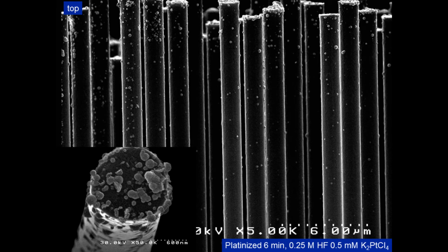Another important point is that if we had a planar photovoltaic silicon cell, if we put enough platinum on there to be catalytically effective, it would have reflected like a metal or blocked all the light. But we don't have to worry about that in this structure because we can just decorate this with little specks of particles of platinum. As long as the photo-excited and absorbed carriers can find the platinum particle before they recombine, then we're good to go, and they can catalyze the fuel formation by this architecture. We showed that worked. We published a paper in Science and another one in the Journal of the American Chemical Society demonstrating the implicit advantages of this part of the architecture for hydrogen production from sunlight by these microwire arrays.